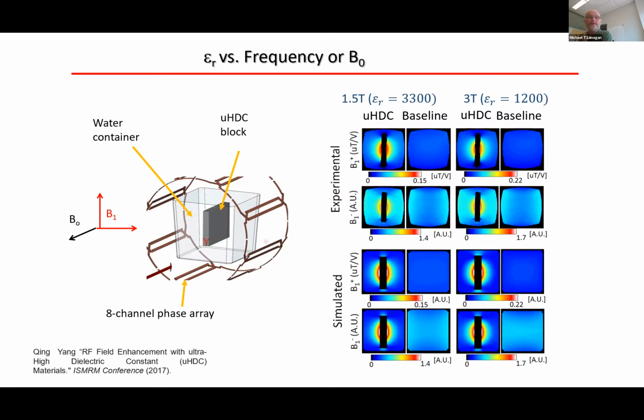So we're actually just looking at one of the faces of this cube, one of the slices, and we're comparing the strength of the signal, that's what this B1 plus is, with and without the dielectric block. So you can see here the intensity gets quite large when we add a dielectric block to the water cube. And then we could also see here the simulations basically show the same thing as our experiment. So again, just another confirmation that this dielectric displacement current is what we're really looking at when we're increasing the signal strength.